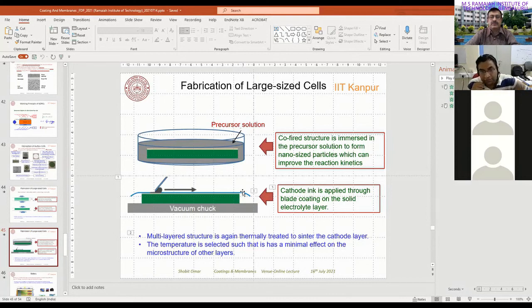What about dispersing nanoparticles? Yes, you use infiltration techniques. What you do is you have a prefabricated porous structure, and this structure is immersed inside the precursor solution. The other way is you can take a dropper and pour the precursor solution, and that solution is basically based on salt.